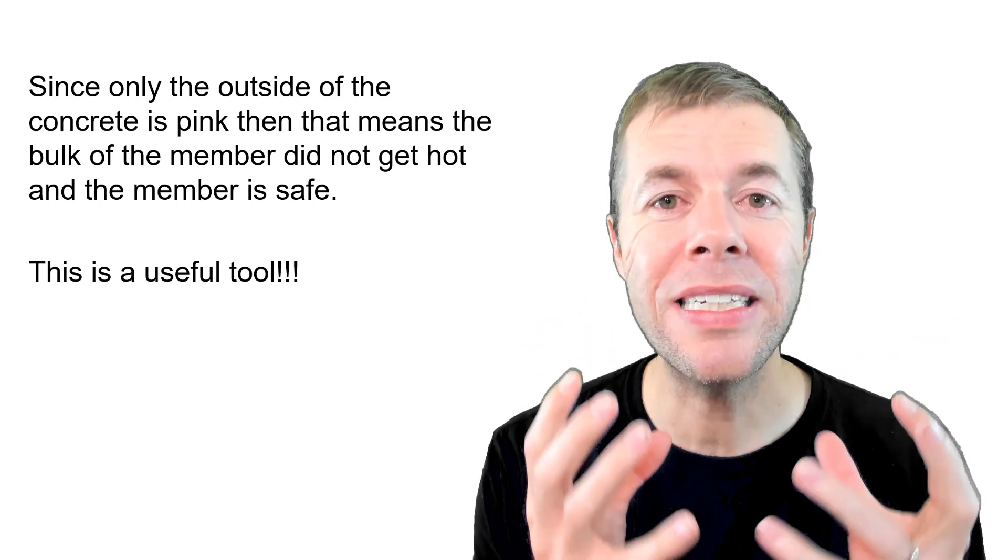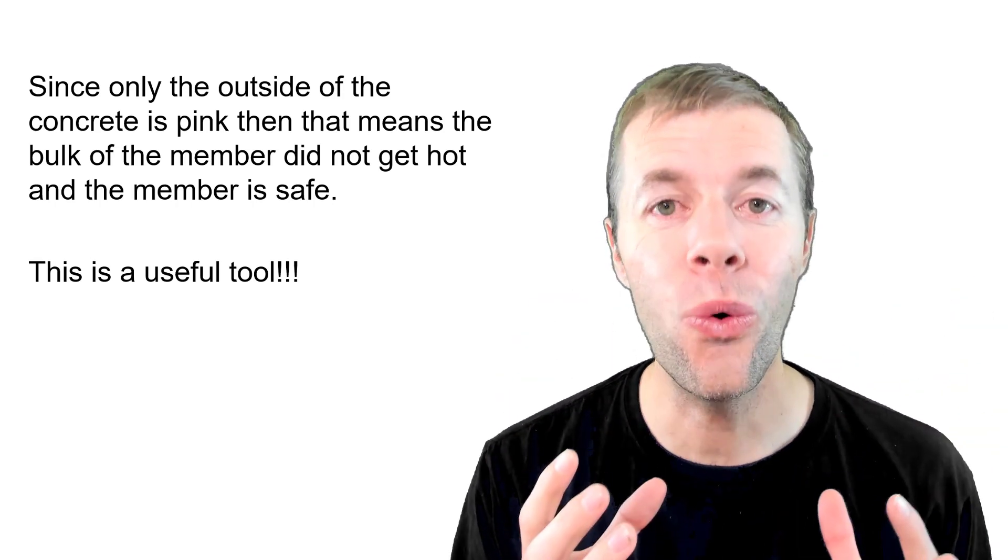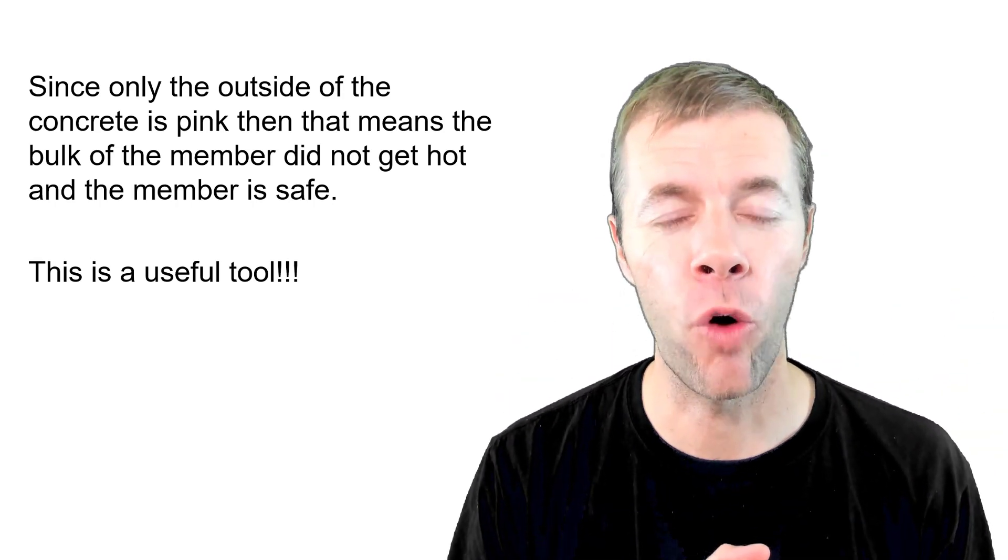This is a crazy useful tool to evaluate how they perform in the field. You'll basically look at the aggregates from the outside of the concrete to the inside. And you should see this color change. Now you can do some testing after the fact if you need to in the aggregate to kind of back into what that color change is. But this is insanely useful to figure out at what temperature and at what depth it's made it inside your concrete structure.